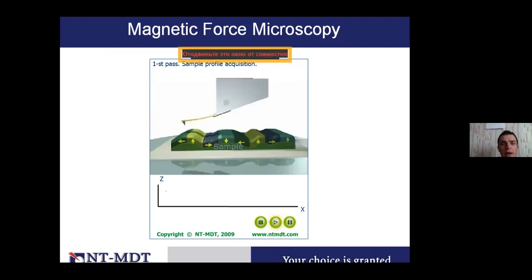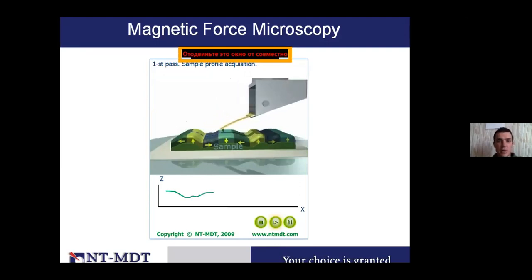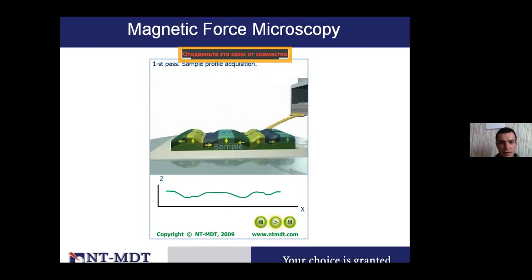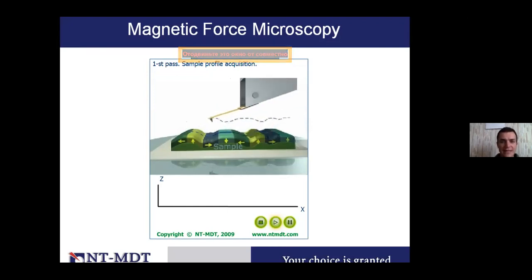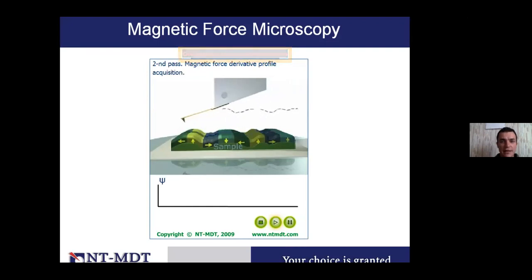So here you can see an example of the other measuring modes to measure the magnetic properties. It's called MFM microscopy, magnetic force microscopy, and you can see how it works. First, we scan the topography during the first pass. Then we return and scan the same line at some distance from the sample and measure some phase shift or magnitude of oscillation, but following the topography